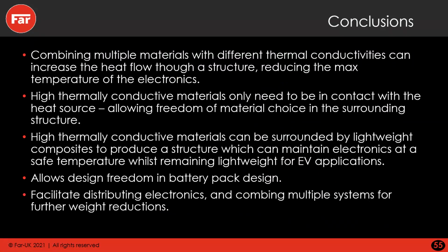So this case study found that we can combine multiple materials together using high thermally conductive materials only where they're required. High thermally conductive materials only need to be in contact with a heat source, which allows freedom of material choice in the surrounding structure. At FAR, we are active in other sectors like aerospace and light rail, apart from automotive.